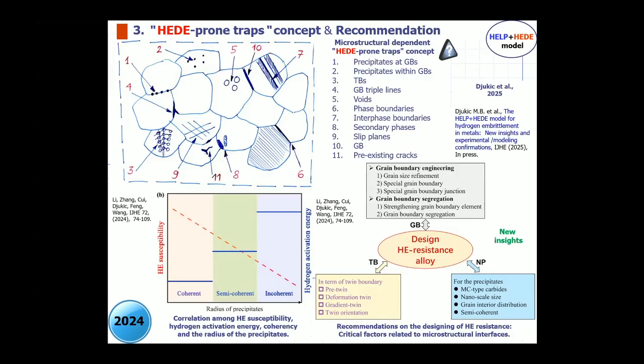And we also analyze the effects of pre-twin, deformation twin, gradient twin, and twin orientation on hydrogen embrittlement. On the other side, MC-type carbides, nanoscale size of precipitates, grain interior distribution, and the coherent precipitates we investigate, and related to grain boundary: grain size refinement, special grain boundary, to improve hydrogen embrittlement resistance, and also strengthening grain boundary elements and grain boundary segregation. So that's the factors which define how to design the material properly.